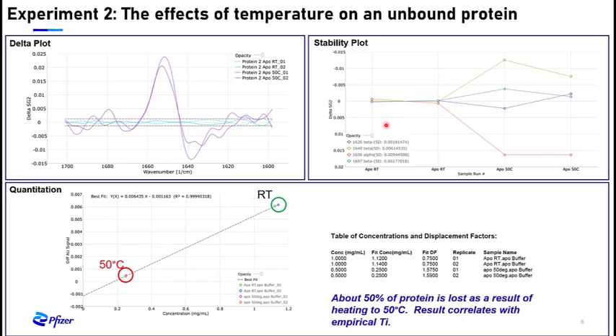To the right of this plot is just another way of looking at the delta plot. This is a stability plot, and it shows the changes that occur in the protein when it is heated to 50 degrees. You see the loss of alpha helical content in the orange and an increase in beta sheet content in the green.